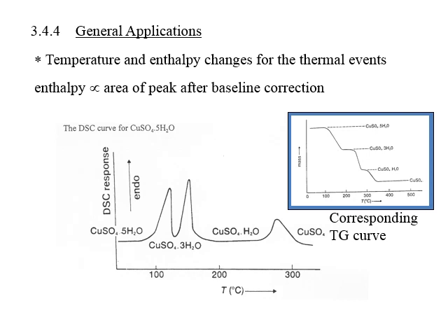And you can see the first an endothermic event, and it's endothermic because you're actually losing water. So you're changing the structure, but you're not crystallizing from a liquid. So we're not decreasing the entropy in this case. But it's an endothermic event where we're going from the pentahydrate to the trihydrate. You can measure the enthalpy by roughly measuring the area of that peak.